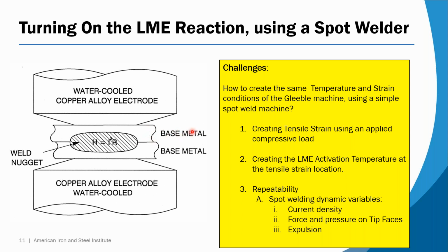So what we want to do is try to create a scenario where we have the same temperature and strain conditions of the Gleeble hot tensile test, but we're going to do it with a spot welder. So the first challenge is to create tensile strain. When we're pushing on the sample, we're putting it in compression. Where's the tension? So we'll talk about that.